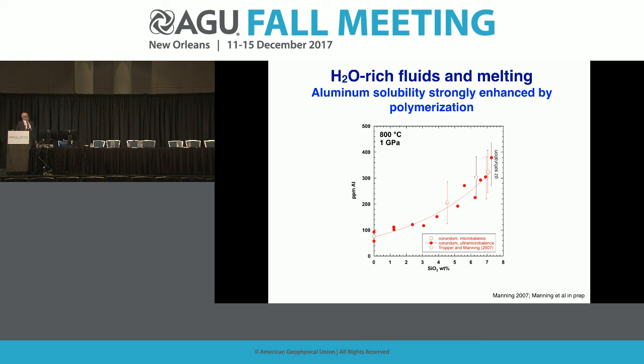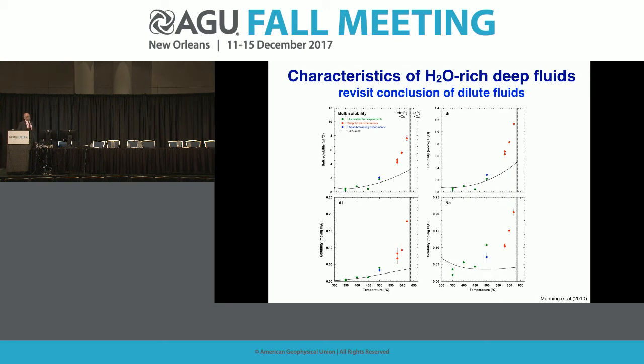And the reason that this is significant is that if you look at the solubility predicted without including anything about polymerization, you would never see this. So the predicted solubility of corundum as a function of SiO2 concentration is shown here. Kyanite would be here, and then quartz would be here. The solubility is much, much higher. And it's entirely because of the interactions between silicon and aluminum, where you simply, in the upper one here, have a substitution of aluminum for silicon to make an AlSi dimer, or something more complicated like this here. That explains the difference in solubility.